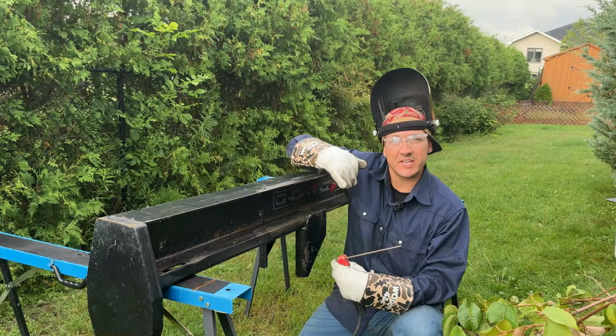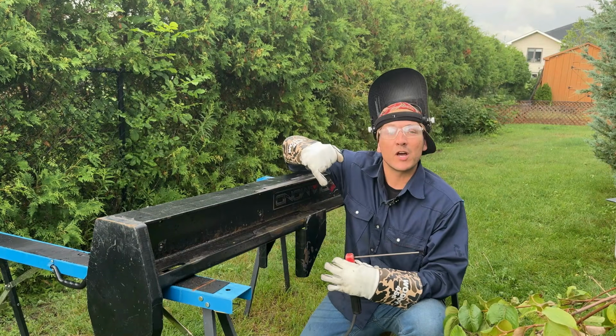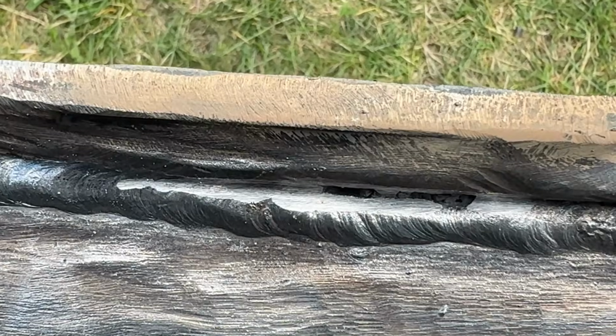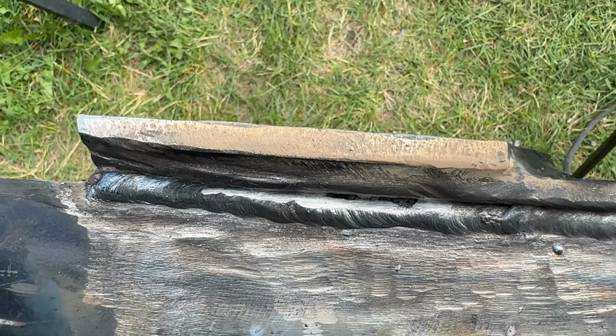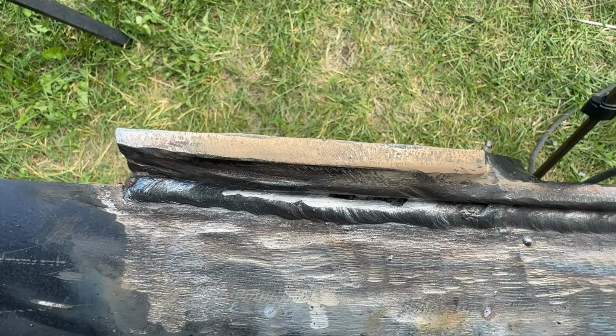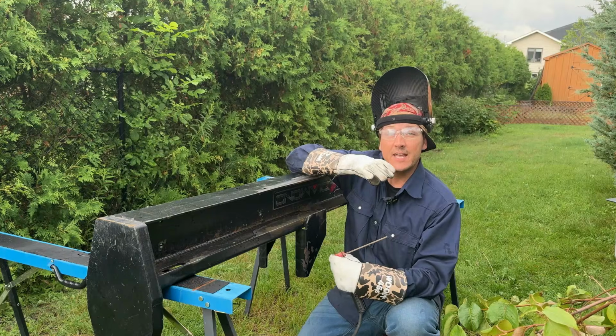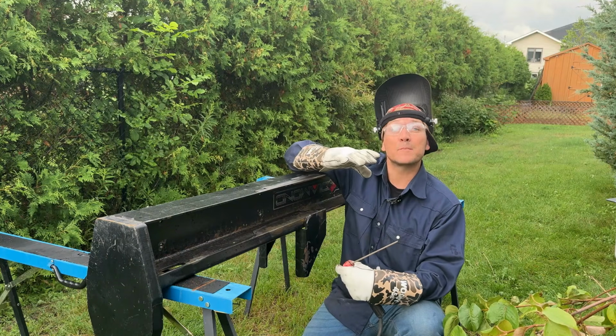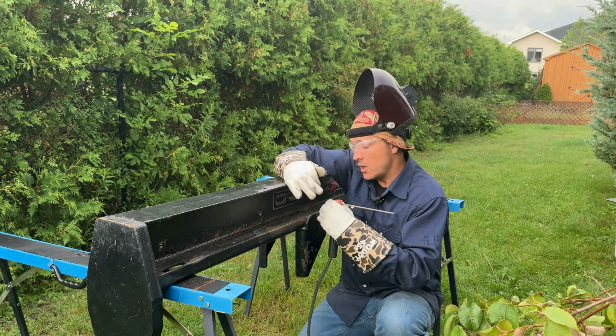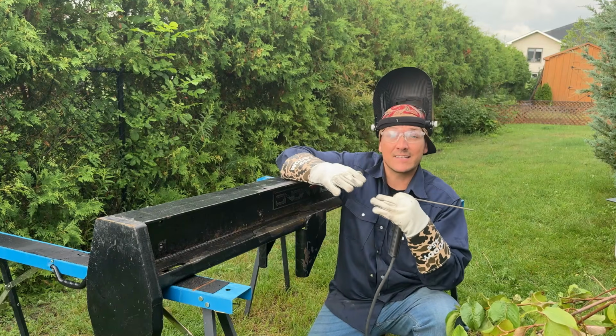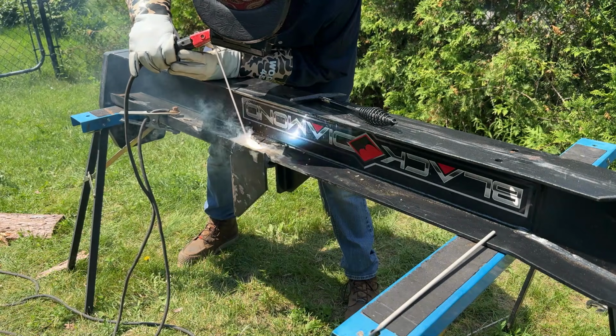And I seen just a hint of slag, so I decided to grind it a little bit further with my grinder, and I exposed that whole weld, and you can see slag that's trapped all the way on the inside, and I had to dig this whole thing out. So I ended up grinding that whole weld out, or at least so much that the slag disappeared, and then I was able to put my new weld in.